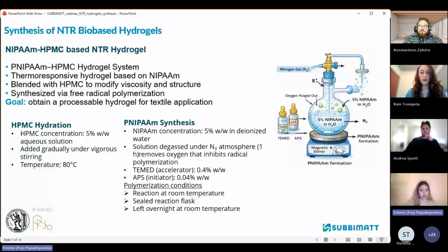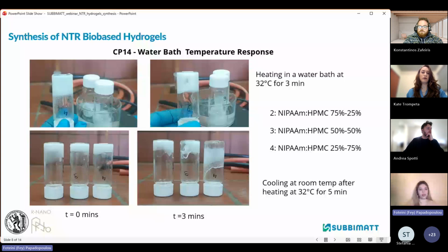So it's a clear gel that when it hits above 32 degrees, you see it gets white. The white part actually represents the kinetics of the polymeric chains and the collapse of the NIPAM structure along with the HPMC. The HPMC and the NIPAM shrink, they release water, so the hydrogel becomes more dense and a harder gel. This is why it stays at the bottom, towards the top upside down bottle, while on the bottom row of pictures, as it cools down again below 32 degrees, it becomes transparent and glides down like a liquid.